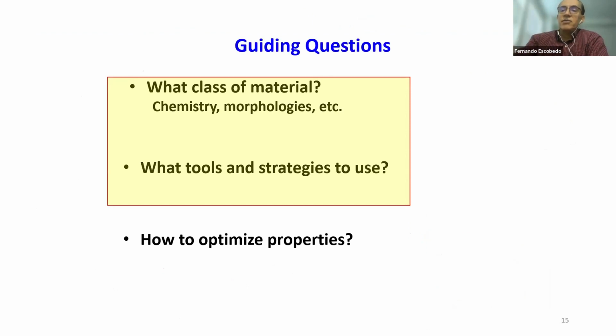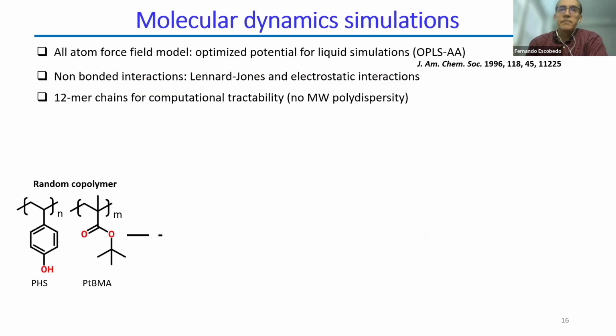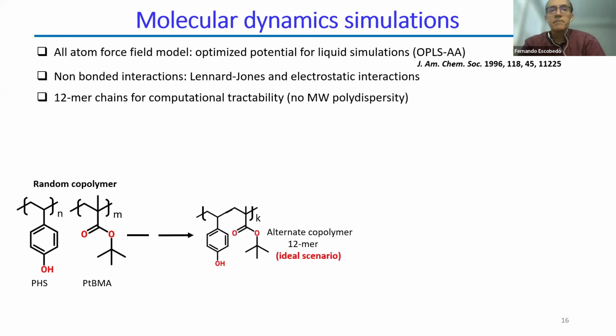So now I want to extend this into some of the methodologies that we want to use. Given that you need this atomistic detail, you have to use all-atom force fields. In the real system, the polymers will have a polydisperse molecular weight, but for our simulations, we chose to use only 12-mers as the chains, all the same molecular weight. It's of course an idealization of the real system, but that allows us to have tractability in our model. But this molecular weight is close to what is used in actual practice. So it's not that small, but certainly it's monodisperse.